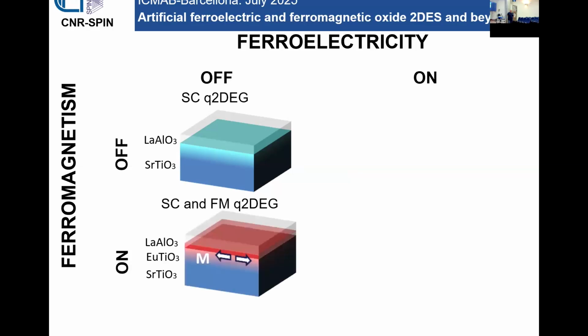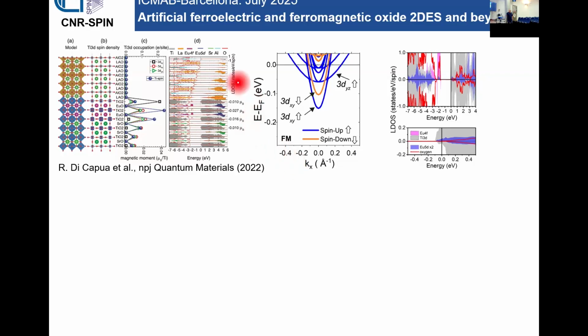Now, at the beginning, we started to modify the properties of this LaAlO3 to introduce spin polarization. And we essentially decided to use delta doping, so essentially depositing between strontium titanate and lanthanum aluminate a few epitaxial layers of europium titanate, which is isostructural to STO, but has a magnetic moment. Europium has a magnetic moment of 7 Bohr magneton per atom. And by DFT calculation, it was demonstrated that the 2DEG is formed essentially in the europium titanate layer, and the titanium states acquire a finite magnetic moment, which is stronger in the europium titanate, but is also present in the few layers of STO where essentially the 2DEG is located.